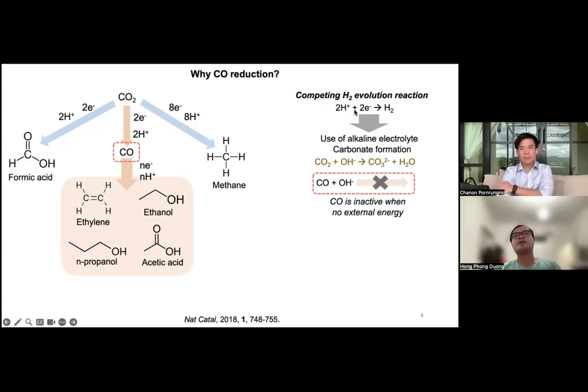Another point is that, considering the electrolyte, the alkaline electrolyte gives a much lower voltage compared to the neutral or the acidic electrolyte, thanks to the high conductivity of the alkaline electrolyte.